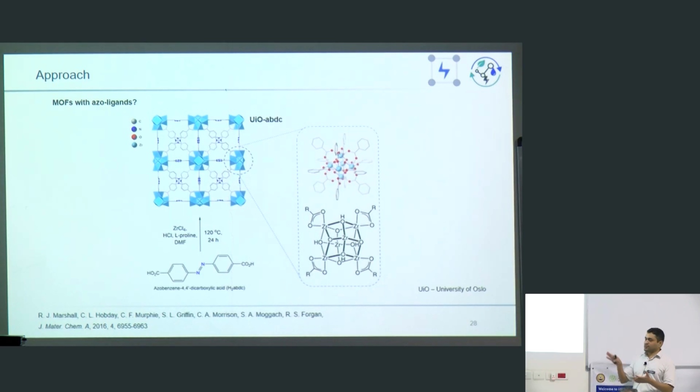It's known to have resistance to different pH conditions. It's thermally stable, as well as having these other properties of porosity, functionality, and other things. So if you produce this particular cluster of zirconium oxygen, it's going to be very, very stable. So if you have to go to the lab and prepare a MOF, and you don't know where to start with transition metals, if you know your ligand donor is carboxylate, a good choice would be zirconium. Just start with zirconium. You're more likely to get a very stable system.